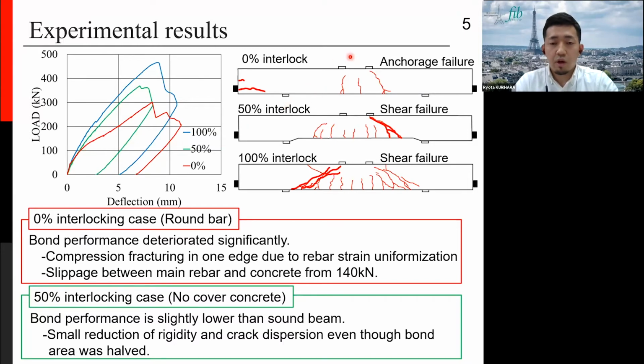The number of cracks was lower than in other cases, and the failure mode of this case changed to anchorage zone failure from the shear failure in other cases. This is because a tied arch was formed in the beam. The tensile stress was distributed uniformly on the main rebars as a tie by bond loss, and a strong compression strut was formed in this area. In the 50% case, the stiffness after cracking decreased slightly compared with the sound one, but rebar slip behavior was not observed, and the crack pattern, crack behavior, and failure mode were similar to the sound one. So it is considered that the bond performance of the 0% interlocking case reduced significantly, but the bond decline in the 50% interlock beam was slight, even though the interlock area was half.